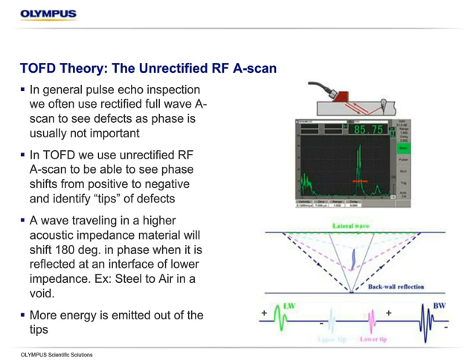We want to be able to see the shift in a signal from positive to negative because this indicates basically an acoustic impedance mismatch. So for example, when we have a steel to air interface, the basic signal would flip from positive to negative.